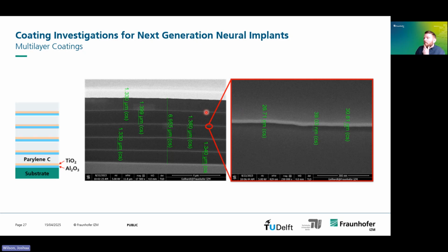So the concept behind this is that the ALD layer is effectively a ceramic, and this forms a water barrier. But the problem is that it's too brittle to really be effective on its own. And so the Parylene offers some kind of mechanical buffer to stop it cracking quite as much, and also from cracking in one plane. So imagine if you had a crack in the ALD that traveled vertically directly through this whole multi-layer structure, then your device isn't going to last very long. Because the water just has a straight line, it will go directly to the electronics, and the corrosion process will begin. What this mechanical buffer does is effectively create a longer, more difficult path, so the cracks are in different places, and it has to travel back and forth, and it slows this process because it's a longer diffusion path.